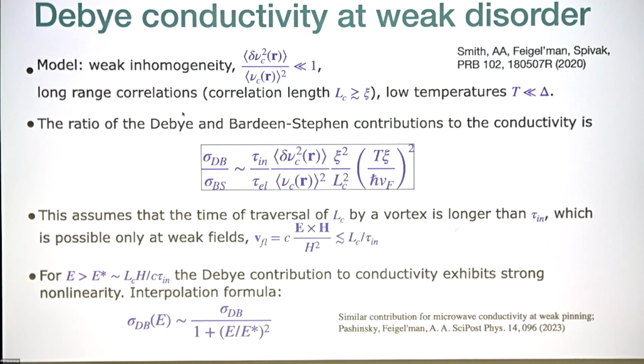If you consider the same low temperature regime at weak pinning, and you study microwave conductivity, the same physics plays a role there. There, the vortices are displaced by the microwave field from equilibrium, and because of the inhomogeneity of the density of states, you get a similar contribution for the linear microwave conductivity. I don't want to speak about it, just mention that it's very similar.